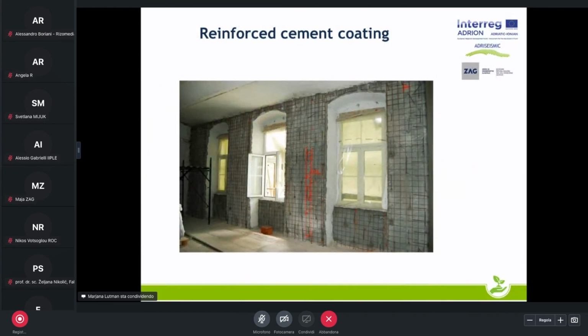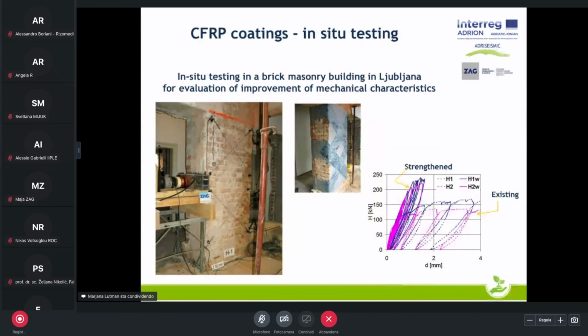The next measure is reinforced cement coating. It is used for stone masonry walls if previously grouted and if there is a need for further increase of load-bearing capacity, or for solid brick masonry which cannot be grouted. As a rule, the coating is placed on both sides of the wall, and both coatings are connected together by means of anchors. In this traditional version, the coating consists of steel mesh in a cement mortar. Besides, carbon fiber reinforced polymer or glass fiber reinforced polymer coatings are also possible and are beginning to be used in Slovenia. In one of Ljubljana's buildings from the 30s, we performed in situ testing and evaluated the effectiveness